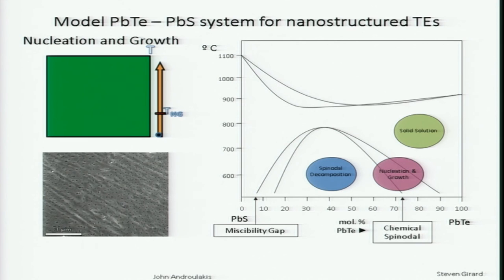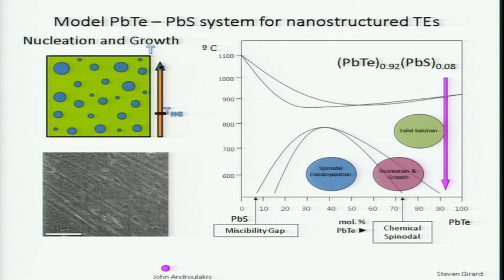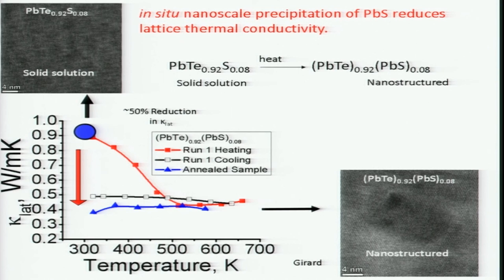So here's the green sample. It's a quenched melt of lead telluride, lead sulfide. We take this, it's metastable, it's homogeneous, and then we start raising the temperature, and the temperature is going up, and suddenly it precipitates all those nanocrystals, the barriers for the heat. And so that material then, it's a very low thermal conductivity material.